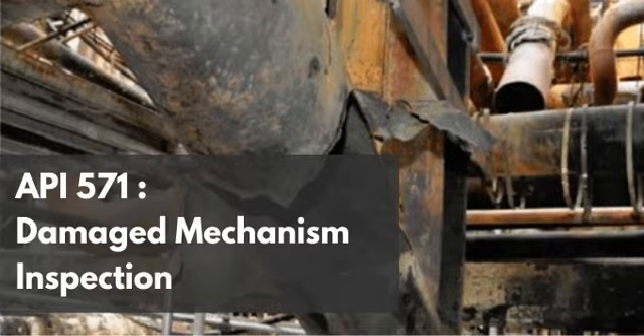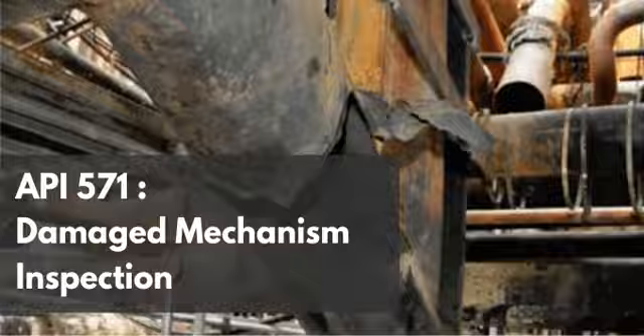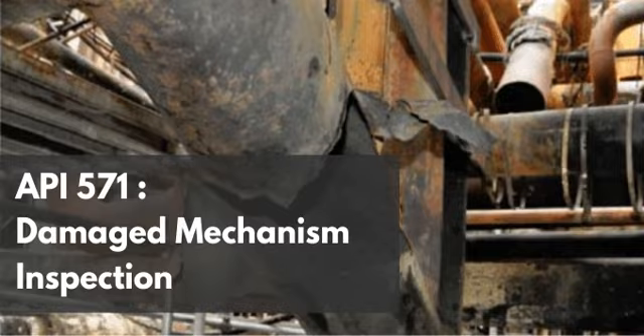When we define carbon steel rigorously, we are talking about an alloy that consists primarily of iron (Fe) with a very small amount of carbon (C). The defining critical characteristic is that carbon steels do not have other alloying elements intentionally added to them to alter their core mechanical or chemical properties. But wait, if you look at a mill test report for standard carbon steel piping, you always see a little bit of other elements, right? It's never just 100% iron and carbon.